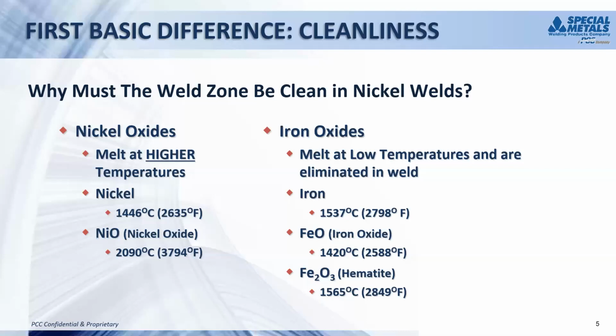If you compare that with steel or the iron oxides, iron melts 2798 thereabouts, and iron oxide FeO is about 2588, and iron Fe2O3 hematite is about 2850 or so. So the iron oxides and the iron base metal melt at about the same temperature. And what that means is that now you can't talk most welders into doing this, but it's possible to weld right through iron oxide, even hot rolled oxide, because the oxides melt at about the same temperature as the base metal. So if there is an oxide present, you basically can burn right through it, or even float it out, or even reduce it. So that's the first basic difference in cleanliness. We've got to remove the oxides. Next slide, John.